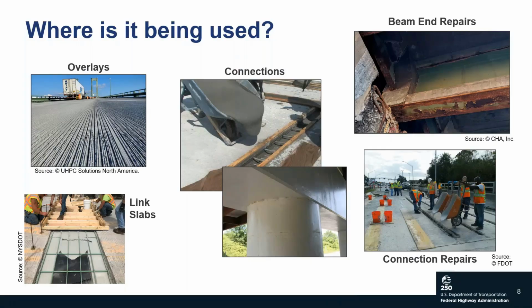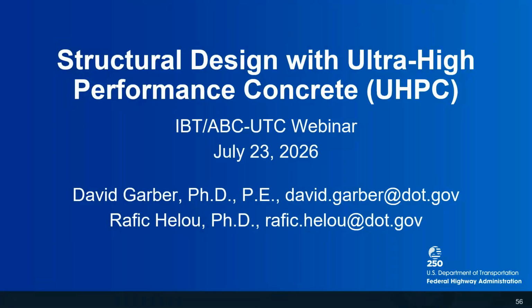Okay. Regarding fiber content by weight, the old connection information had a 2% lower bound. Is this still required? I think that maybe this referred to the ABC guide spec that was published in 2018. In the 2018 guide spec, the material section doesn't have any tension property requirements or criteria. So I guess the guide spec was developed on certain mixes and had a 2% fiber criteria. The updated UHPC guide spec doesn't have any minimum fiber content criteria, but it does have the tension property criteria. So if you're doing connection designs, I think it's still okay to use the criteria that are in the guide spec. If you wanted to also test your tension properties and use the UHPC guide spec, then you could do that as well.